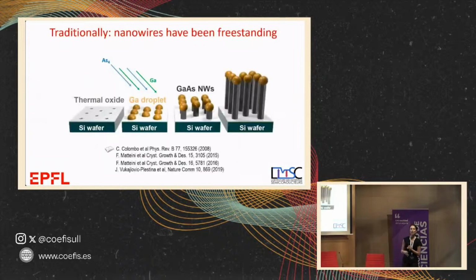So you've seen these freestanding nanowires, and these freestanding nanowires are traditionally obtained freestanding, and you'll see later on why we stopped doing this freestanding structure, because even though they're beautiful, they are much more difficult to implement in devices. And how this works is that you start with a wafer, you make some holes, you have an oxide, and this oxide is a material that the atoms don't like at all.